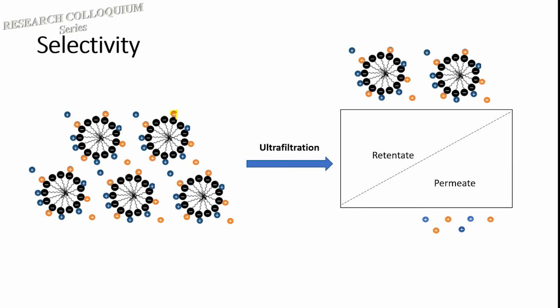So eventually, if your solution contains, let's say, 2 different types of cations, all those metal cations are electrostatically bound onto the micelles. And all these micelle metal complexes are rejected in the ultrafiltration process. In other words, we can get very good rejections, isn't it? For this metal mixture, we get above 90%. But unfortunately, what we want to achieve is to separate between cations A and cations B. Is it possible to separate them?